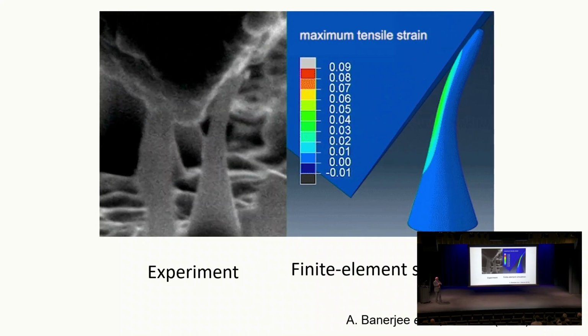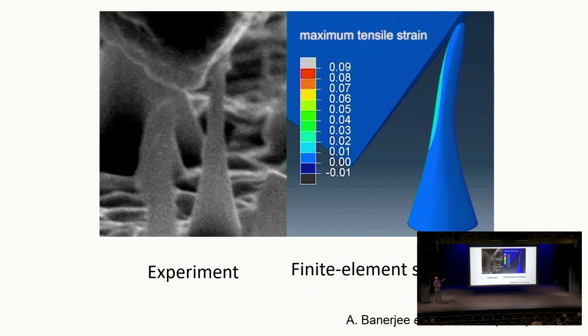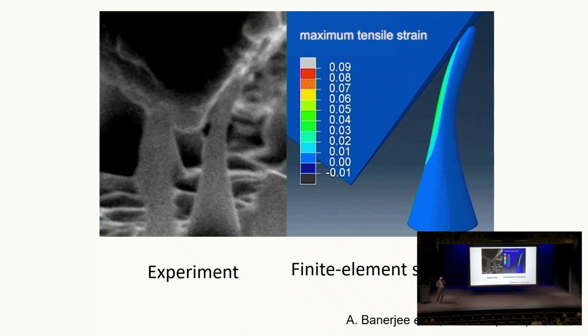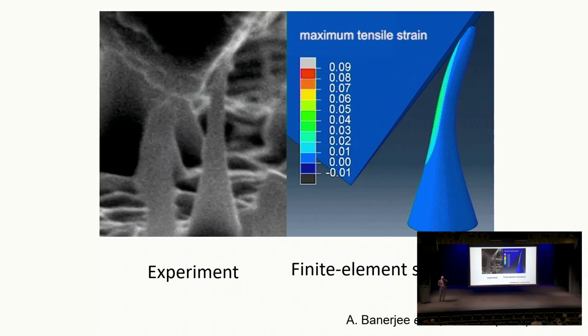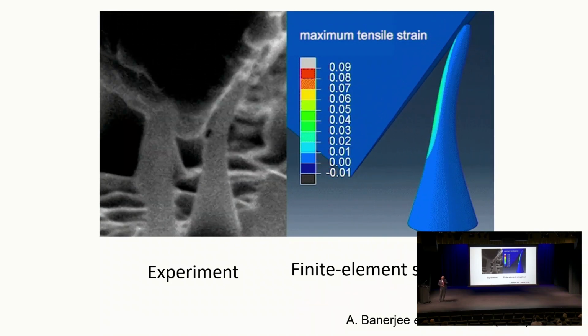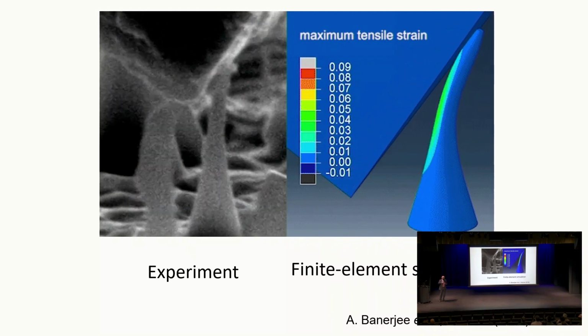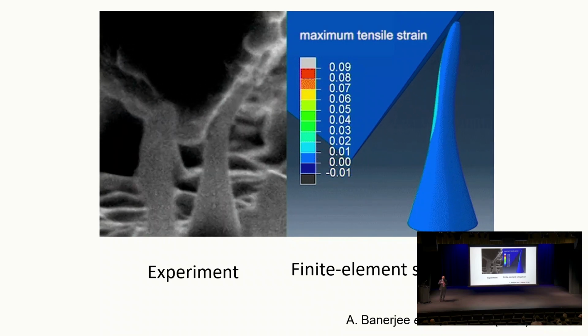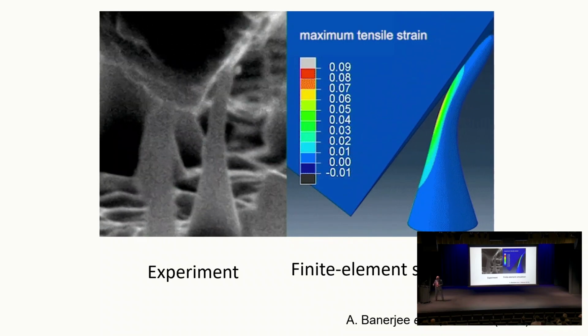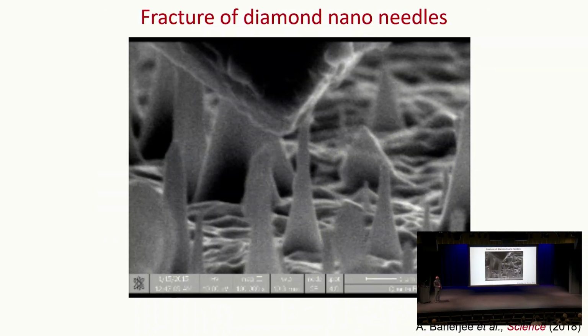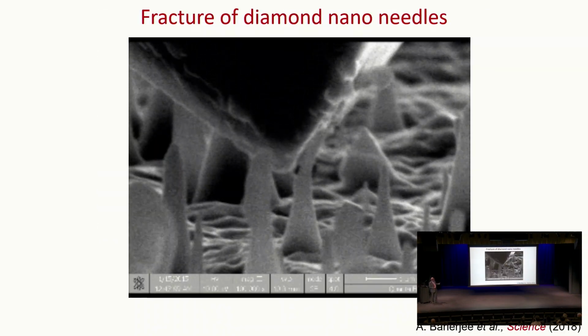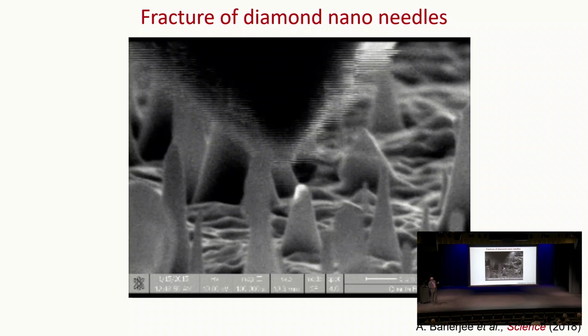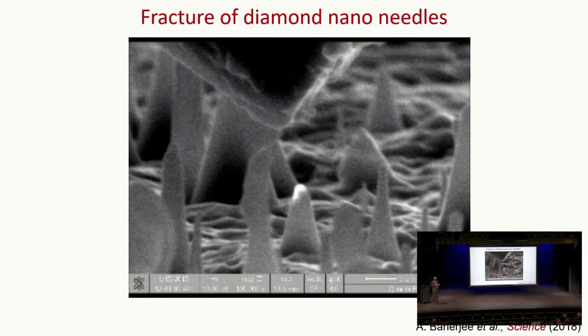We had to be very careful with friction. So could friction play a role? Because diamond to diamond friction. So in the finite element simulations, we put in friction coefficient of 0.1 or friction coefficient of 1. It turns out it makes no difference. And also we know the stress strain curves, or force displacement curves, they show very little hysteresis, which is an indication of friction. So having done this, now this is polycrystalline diamond, and you can see catastrophic fracture at about 4% strain. So single crystals, we can push them to 9% strain, and polycrystal diamond, you can strain them up to 3 to 4%, which is pretty surprising.